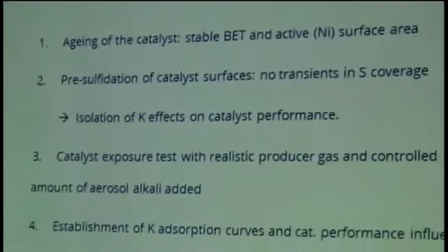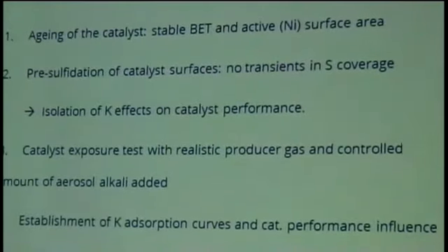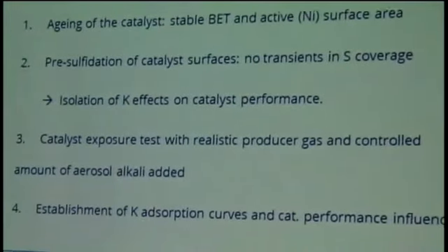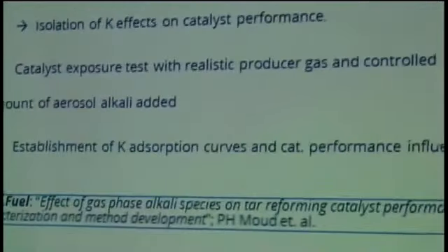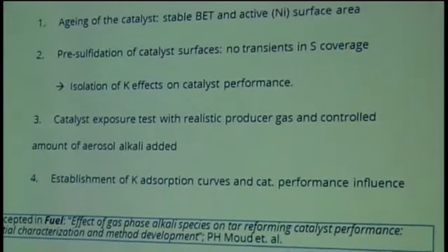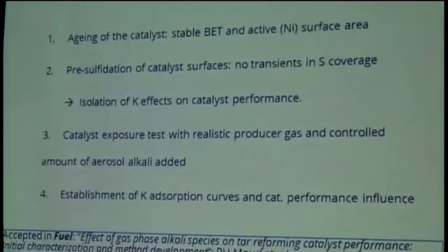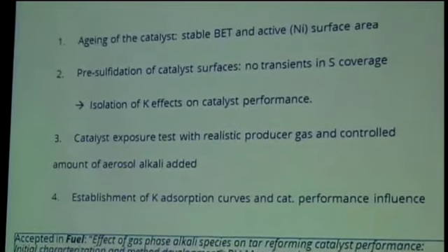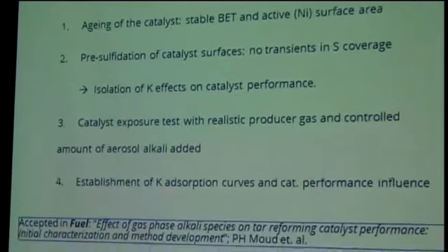So, to conclude this work, together with KTH, there's been development of a methodology for looking at surface and gas phase alkali interaction, and this could be any salt. In this case, we'll start out with the alkalis, but you could imagine phosphates and others as well. It includes aging the catalyst, pre-sulfiding it, and then we expose it to realistic producer gas, adding aerosols, and currently ongoing is establishing various potassium absorption curves and the influence on catalyst performance.